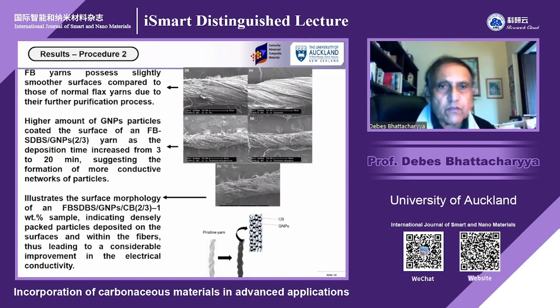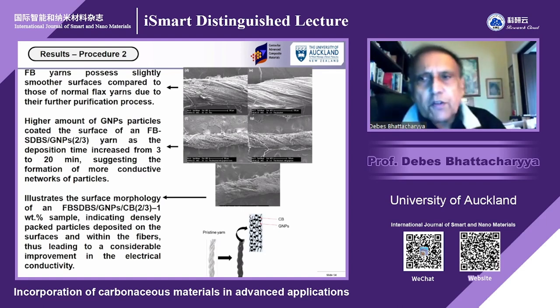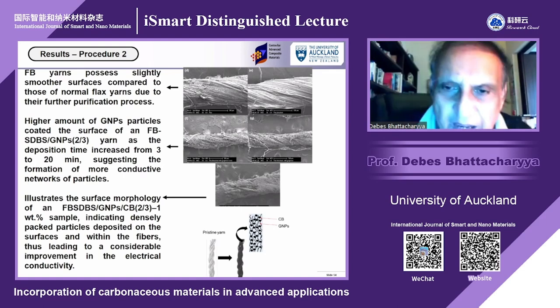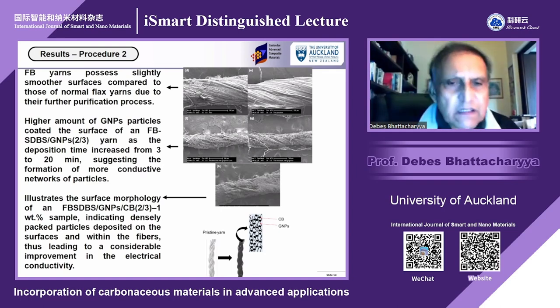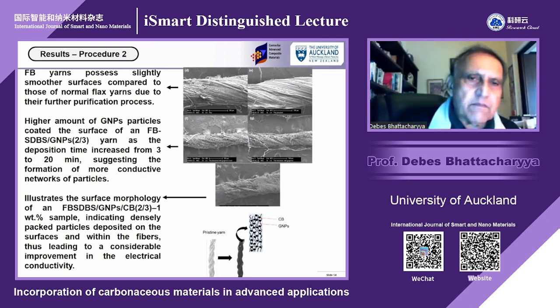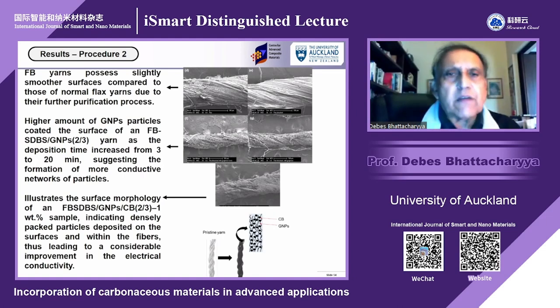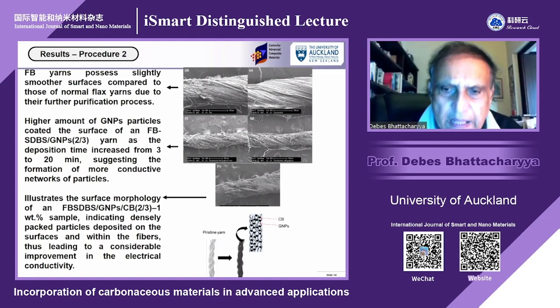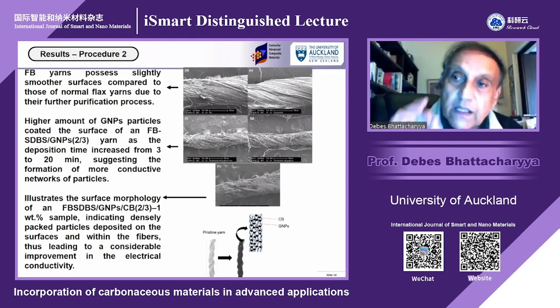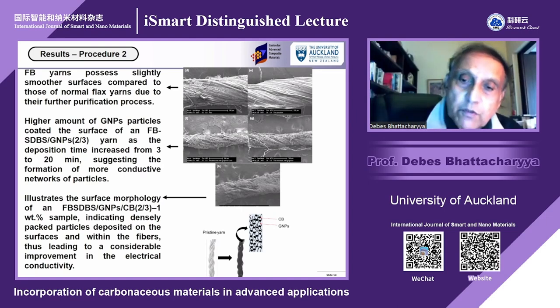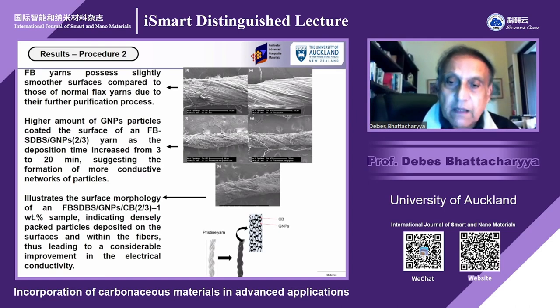We increased from 3 to 20 minutes, and these are the process parameters you can play around with. There is nothing fixed. You can say, I will do it for 15 minutes. Somebody will say 25. I'm trying to show a trend there, that if you increase, you will improve that. But the basic principle is very important, that carbon black is going between those